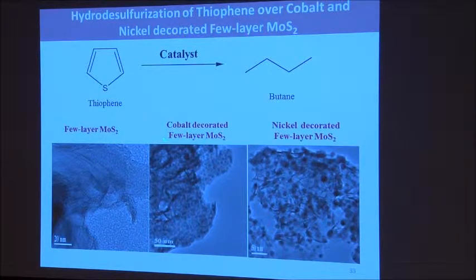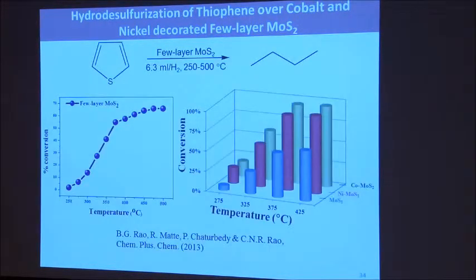We have done that with a single-layer or two-layer MoS2 by itself, or by putting a few nanoparticles of nickel or cobalt on it. By doing that, we actually find tremendous improvement. These nanosheets of molybdenum sulfide with these nanoparticles really do hydrodesulfurization very effectively.